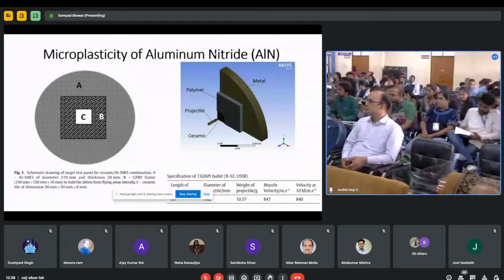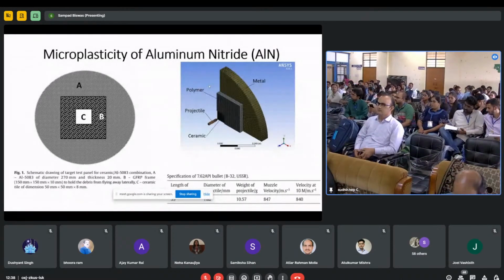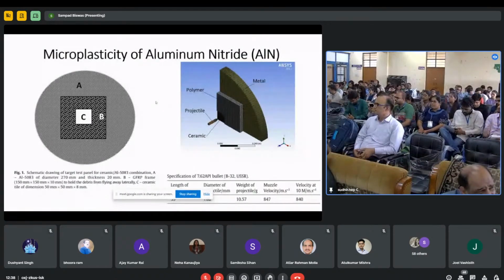So we carried out an experiment with two different ceramics. One is aluminum oxide, the other is aluminum nitride, and we wanted to see how this varies with the type of ceramic, with the chemical composition of the ceramic. So one is AlN, the other one is Al2O3. Those two have two different crystal structures. One has a hexagonal crystal structure, the other has a rhombohedral crystal structure.